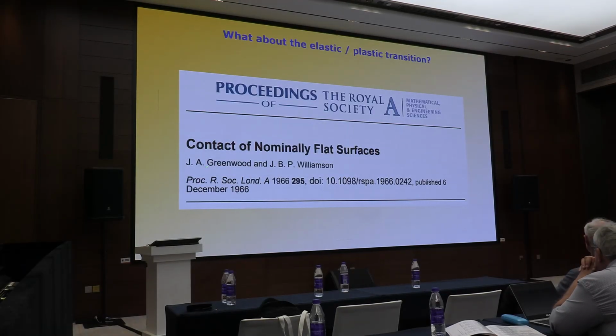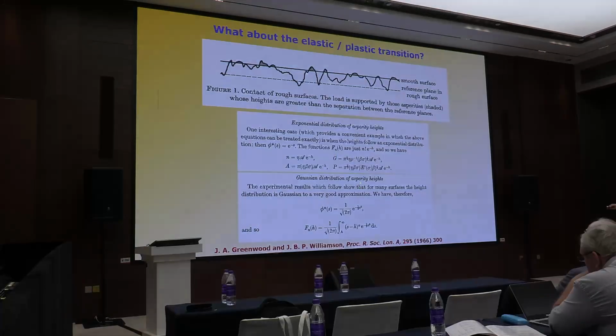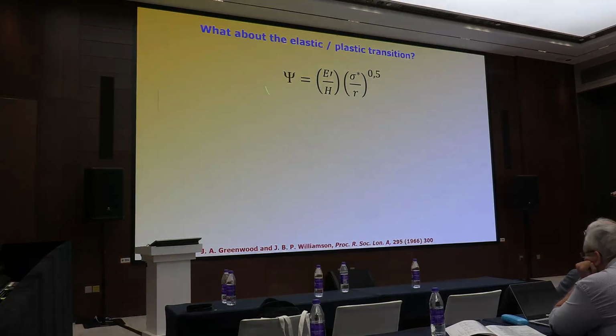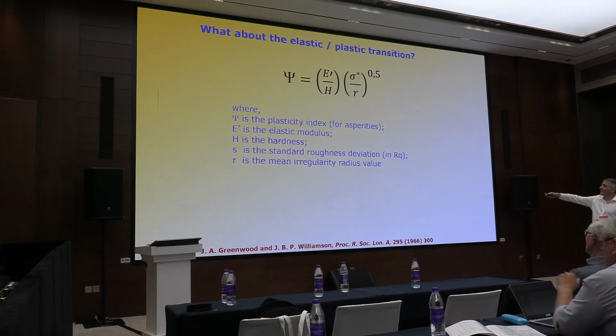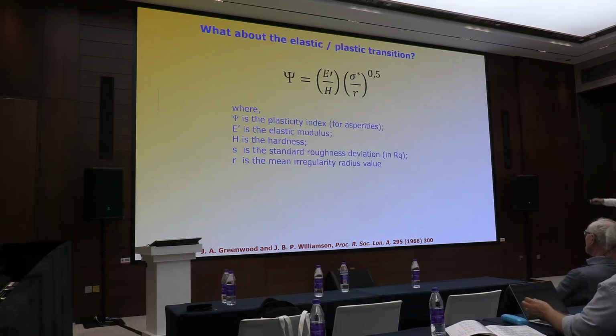Posterior work from Greenwood and Williamson discussed the contact of flat surfaces. I said we have the elastic regime and the plastic regime, and where is the transition? In this work, these researchers studied the transition between elastic and plastic behavior. They analyzed with statistics the roughness of different surfaces, defined different ways to define roughness, and at the end proposed this equation. This is the plasticity index that depends on the elastic modulus, the hardness, the standard deviation of roughness, and R, the mean irregularity radius value.